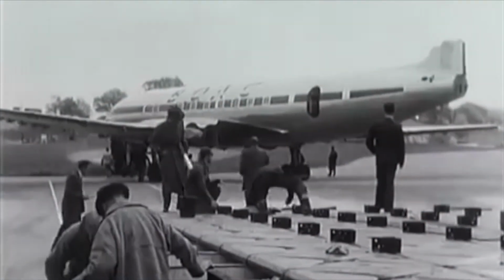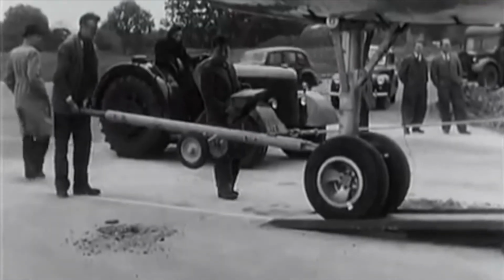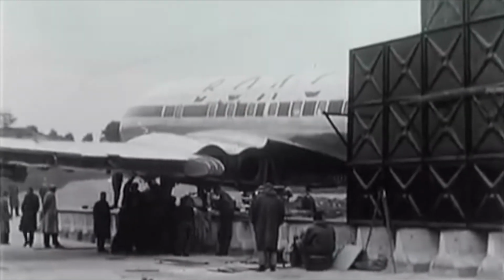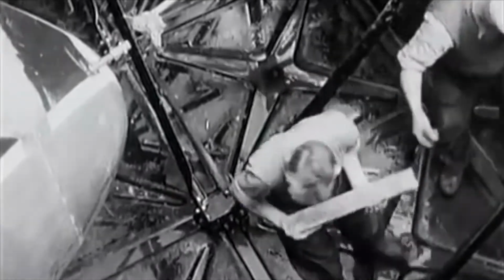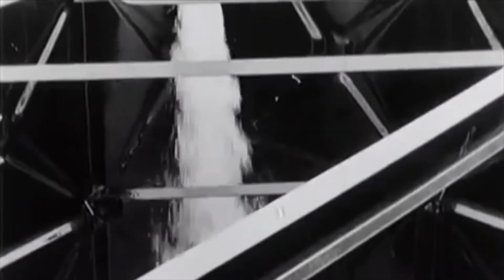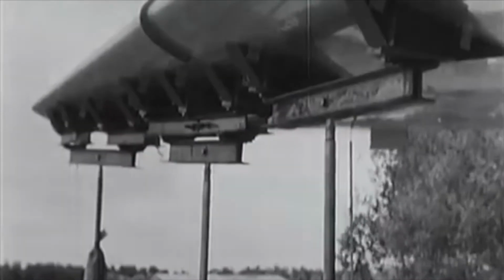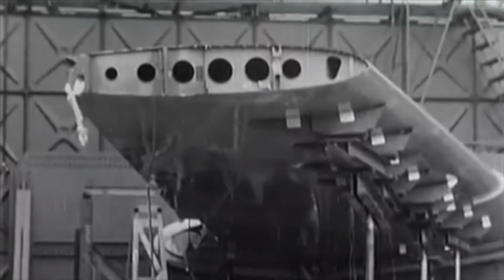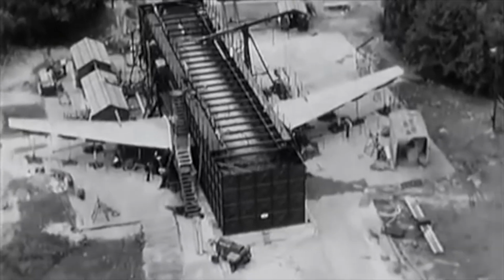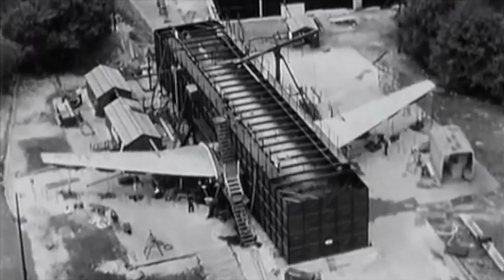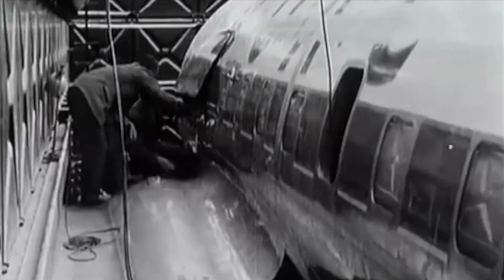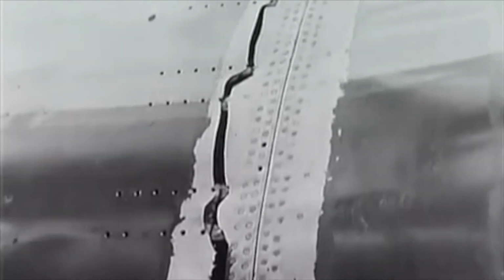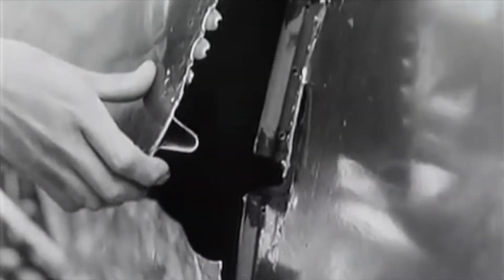The most intensive probes into the Comet disasters have been carried out at the Royal Aircraft Establishment at Farnborough. One of them involved the testing to destruction of a Comet, seen here being placed in a special water tank with airbag seals at the points where the wings project on either side. The tank holds 200,000 gallons of water. After it had been filled, jacks beneath the wings caused a series of bumps as if in flight, and internal pressure was raised in the fuselage. After the equivalent of 5,000 3-hour flights, metal fatigue resulted in cracks and breaks. Information obtained from many scientific tests will, it's believed, lead to new Comet triumphs in the future.